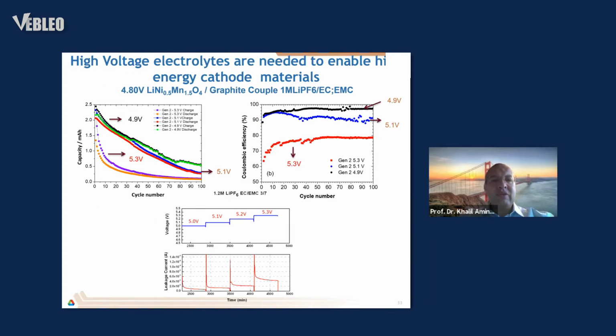On the electrolyte, as you know, if you operate at high voltages using conventional electrolyte like EC, EMC, when you start operating at high voltage, you can see the capacity drop almost to zero, and the efficiency drops significantly. If you take, for example, this high voltage cathode and graphite, and do a floating test at different voltages, you can see that the leakage current is going up, which means decomposition is happening.